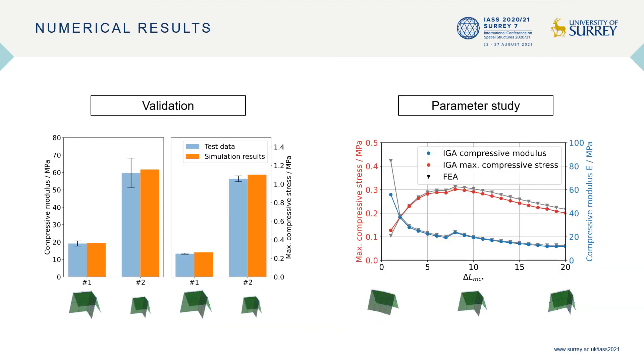For validation of the numerical setup, we also performed mechanical tests of two different Miura-Ori geometries under compressive loading. The numerical results were then compared to the real test data, and you can see on the left that there is good agreement between the results for compressive modulus and maximum compressive stress. So the model is validated for the compressive load case.